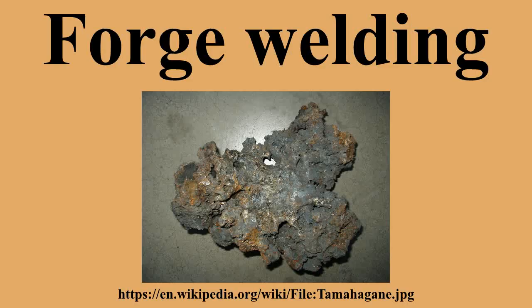Most ancient forge welding began with hyper-eutectoid steel, containing a carbon content sometimes well above 1.0%. Hyper-eutectoid steels are typically too brittle to be useful in a finished product, but by the end of forging, the steel typically had a high carbon content ranging from 0.8% to 0.5%.